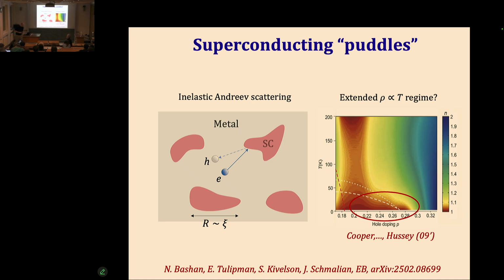In some sense, these questions are dual to each other, right? So you ask what's the low energy excitation that's causing the scattering, or what's the singularity in the scattering matrix element. So you can say if I start from some low energy excitation, like some spin fluctuation or these superconducting islands, and I integrate them out, they're low energy, so they produce some singularity in the scattering matrix element.